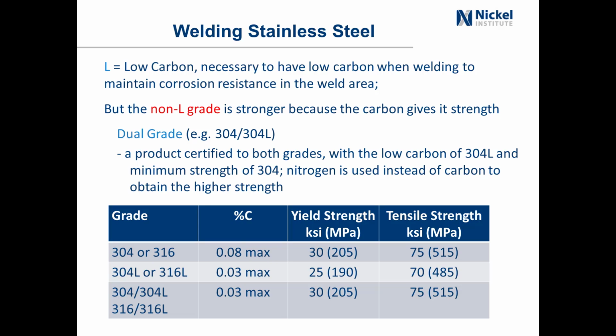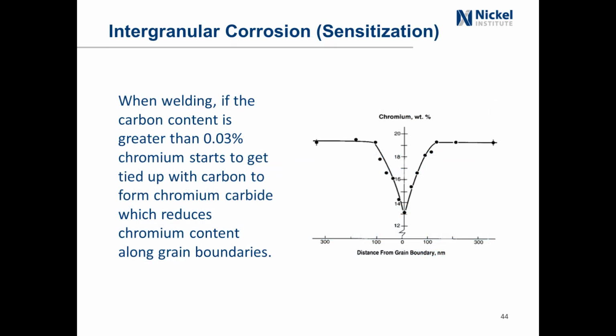And why do we talk about L grade versus non-L grade? That's because there's the process of sensitization. When you're welding, if the carbon content is greater than 0.03, chromium starts to get tied up with carbon to form chromium carbides at the grain boundaries, which reduces the amount of chromium content along the grain boundaries. So now you've got less chromium, you have less corrosion resistance along the grain boundaries.